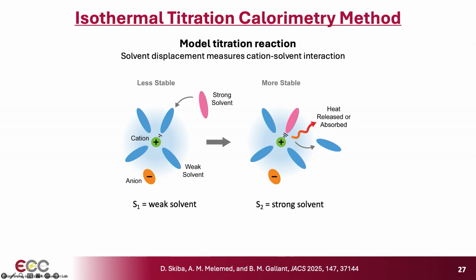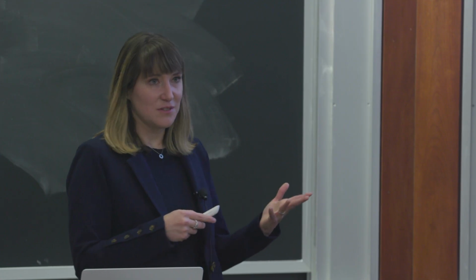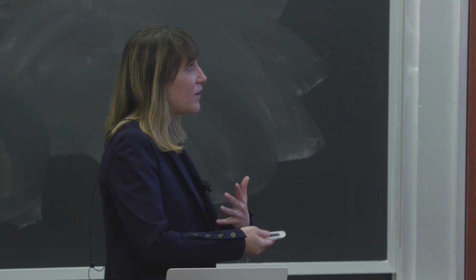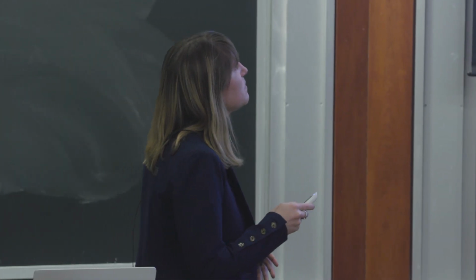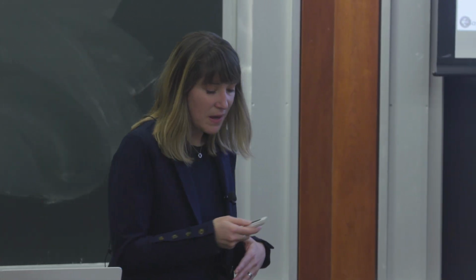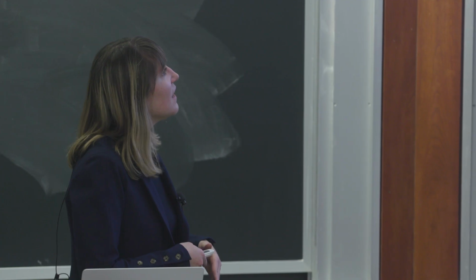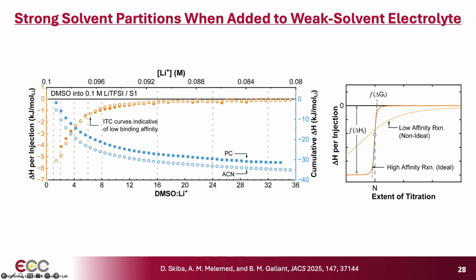So we proposed an analogy to an electrolyte. In our analogy, the lithium cation is acting like the macromolecule, and it's initially dissolved in a weak solvent, or S1, and we inject a strong solvent, S2. So if a preferential coordination event occurs, there will be a displacement reaction with some heat signal, and then we can track that and hopefully pull out the thermodynamics of that exchange reaction. Okay, so that will tell us exactly what drives preferential coordination between two species in competition.